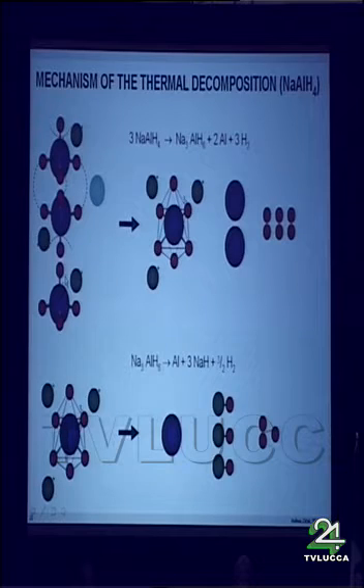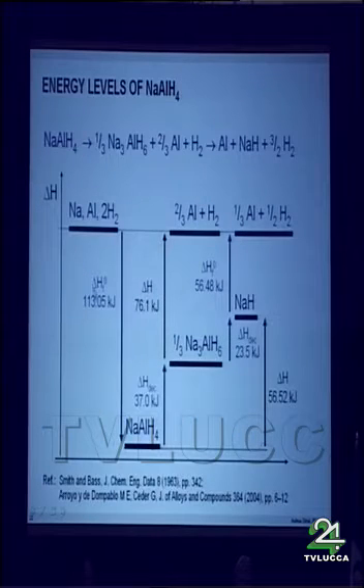It is for sure that hydrogen has to be transferred between different atoms in the structure in order to form the intermediate compound, and at the end hydrogen binds to the other element, and this is also true for all the complex hydrides. The hydrogen at the end is no more on the same element as it was in the beginning of the structure, and that means in order to make it reversible we always have to overcome the barrier to dissociate this, in this case here sodium aluminum hydride, in other cases lithium hydride. Energetically, it looks like that.